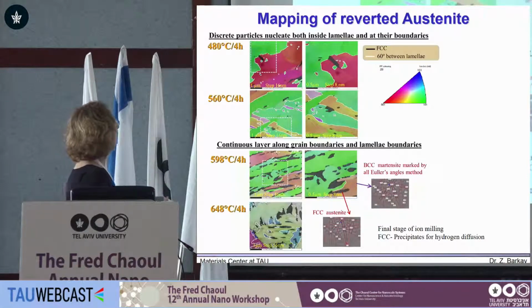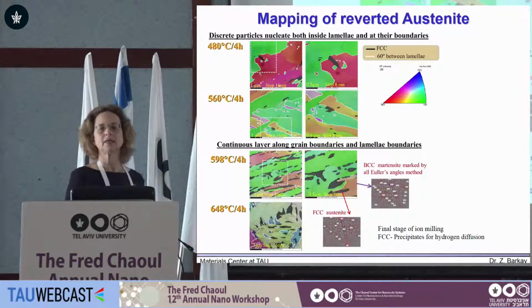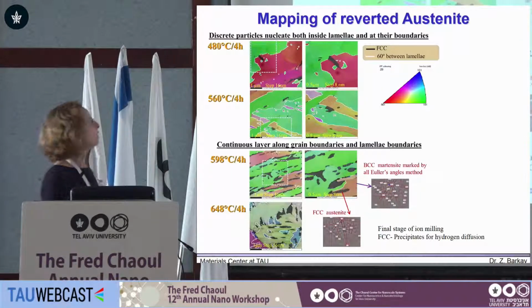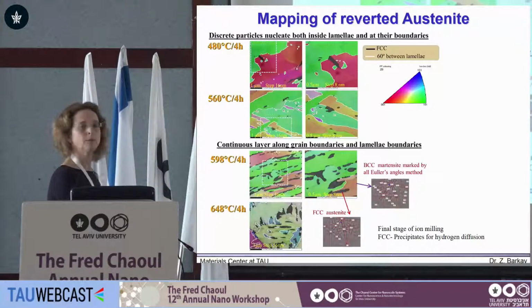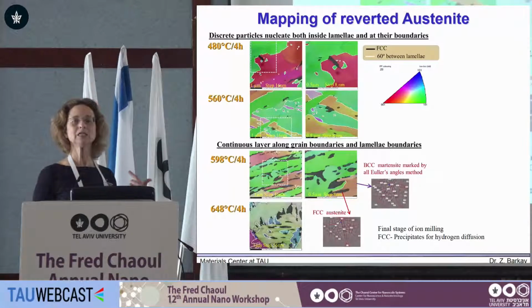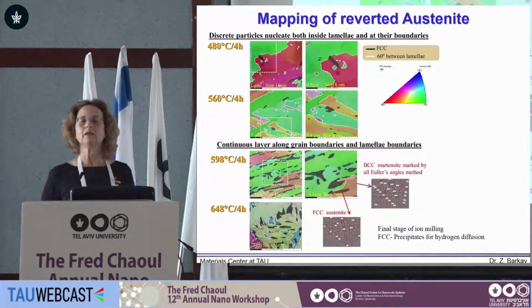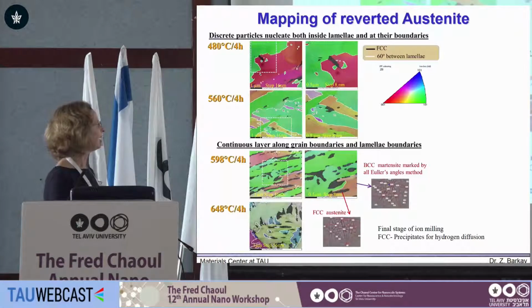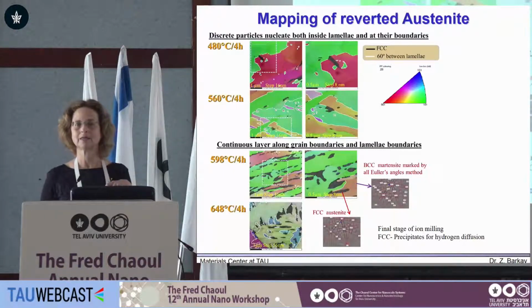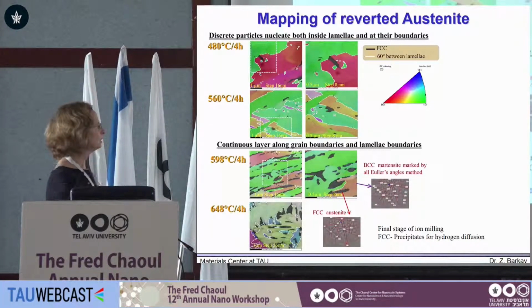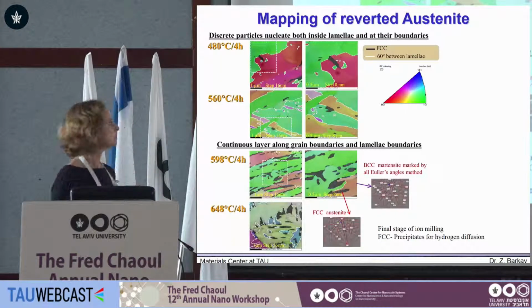What we see here is the mapping of reverted austenite in the martensite matrix, shown in gray. You see that as the aging temperature increases, we have much more population of this phase. In addition, what is very important in TKD is the localized information of where this phase sits - it's not just XRD that can tell you that it exists or increases, but the position where it is.